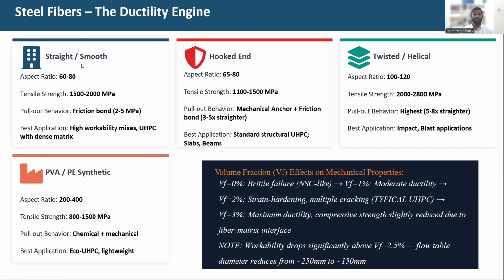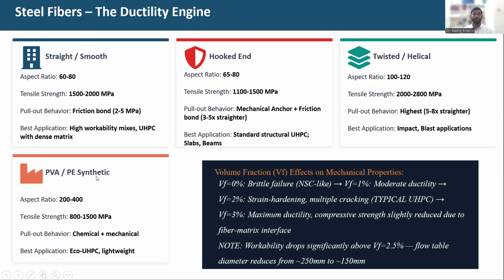And coming to the aspect of steel fibers, we have different steel fibers that are currently available in the market, particularly the straight fibers, which we also call smooth fibers, hooked end fibers, twisted and helical fibers, and PVA and PE fibers, that is particularly the polyvinyl alcohol or polyethylene synthetic fibers. Among all of these fibers, it is proven that either straight fibers or hooked end fibers are yielding better strength. Again, combining hybrid fiber combinations also gives much better tensile capacity and a much better structural perspective. But in real-time scenarios, we mostly try not to use the helical type of steel fibers or PVA or PE type of fibers, primarily because of the cost aspect, and also the production is very less compared to the straight fibers and the hooked end fibers.